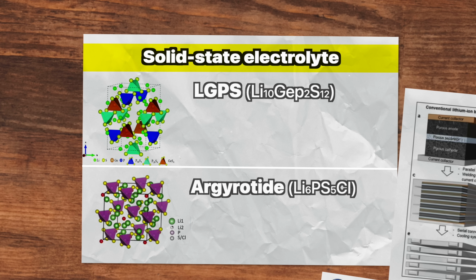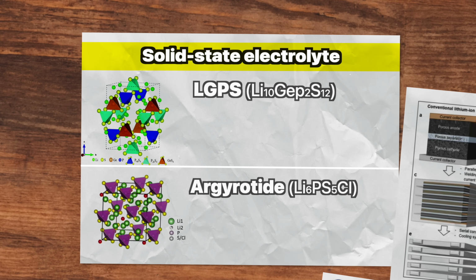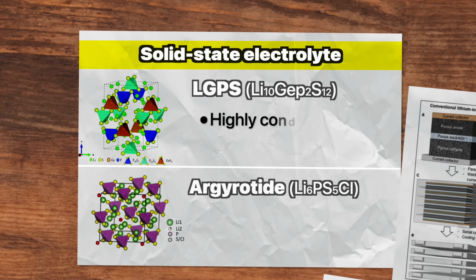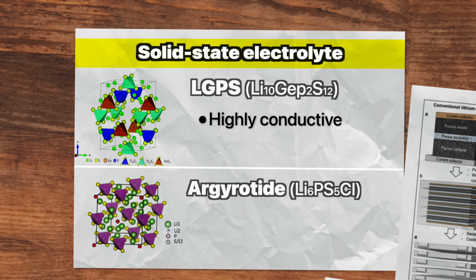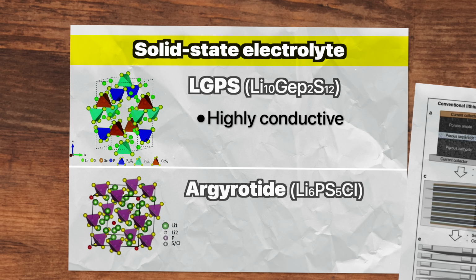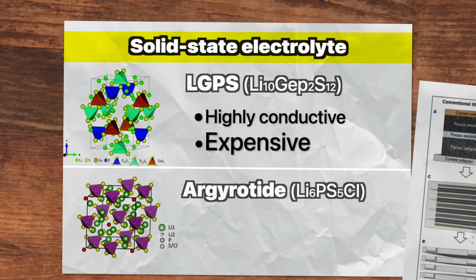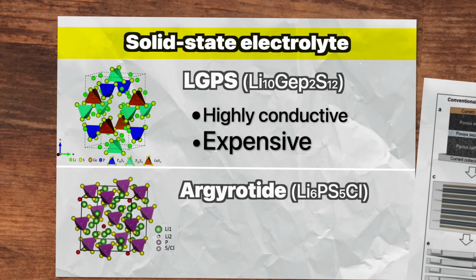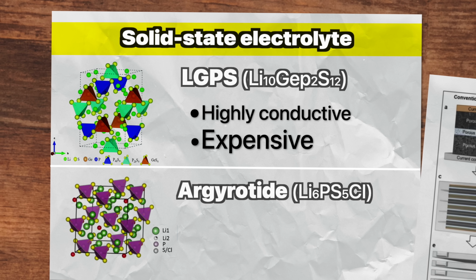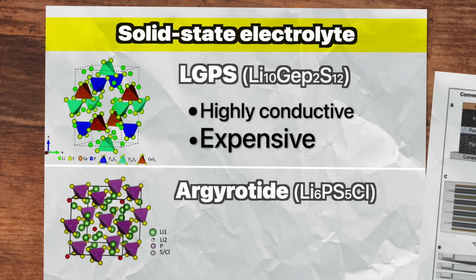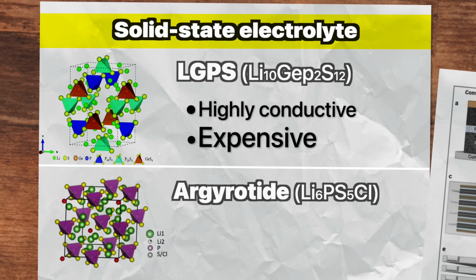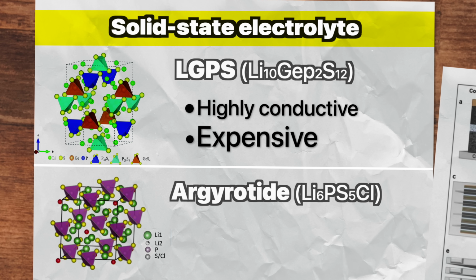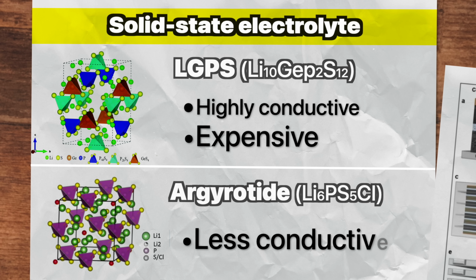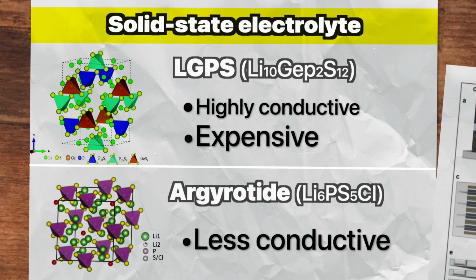Obviously. SABERS batteries use one of two lithium-rich solid electrolytes. One, LGPS, which is highly conductive and allows high-power batteries. The problem is that it has germanium, which costs 10 times more than silver because it's hard to extract. This makes this electrolyte expensive and possibly only viable for space missions where price isn't that important. And two, argyrodite, which is far cheaper, but it's also less conductive, so you get less power.